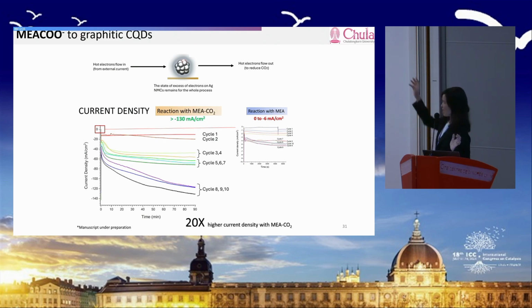Just trying to explain by the top figure: we have electrons coming to create the state of these electrons on the silver, and the actual electrons will flow out to reduce carbon dioxide, and we draw more electrons. So that's why our current density increases, higher and higher. And that's the one we use in the presence of CO2. Without CO2, if we just do this with MEA, even for 10 cycles, it's negligible current density that we observed.